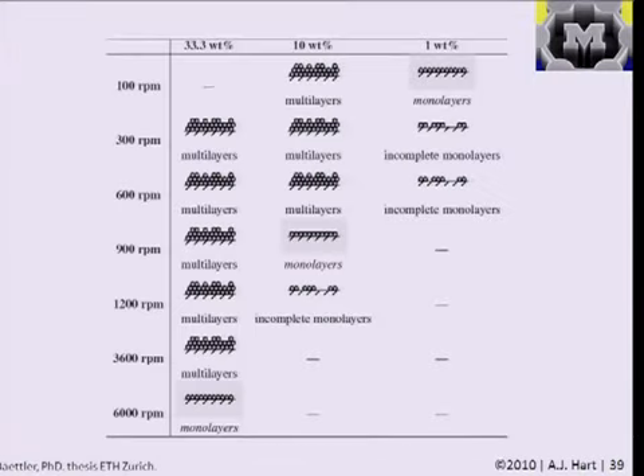And this is a plot from that thesis that just shows some different conditions that resulted from, for example, varying the spin speed in the deposition process and varying the concentration of particles in the solution. If you vary the spin speed, in this case we're going from 100 RPM to, say, 600 RPM, so a factor of 6. You can imagine that at low spin speed for a particular concentration, you might have better packing of the particles, but you're not going to throw the particles off fast enough, so you would have more layers than you would in the case of a high spin speed.